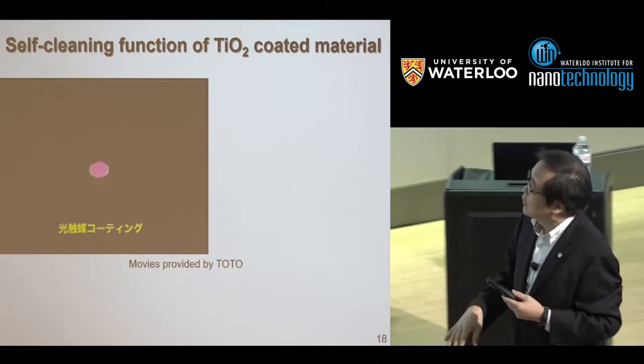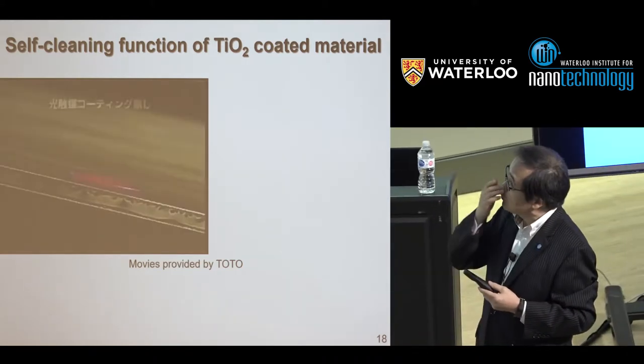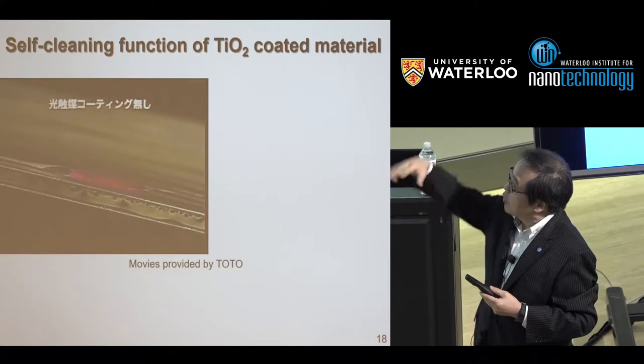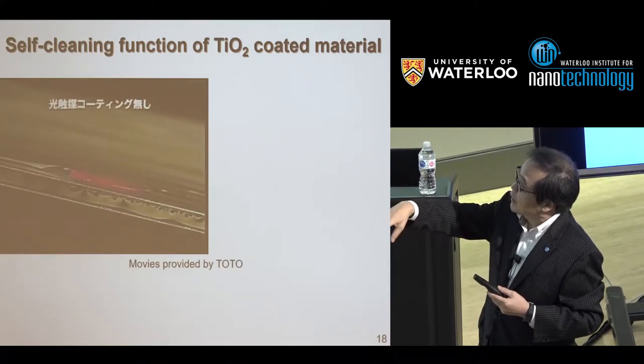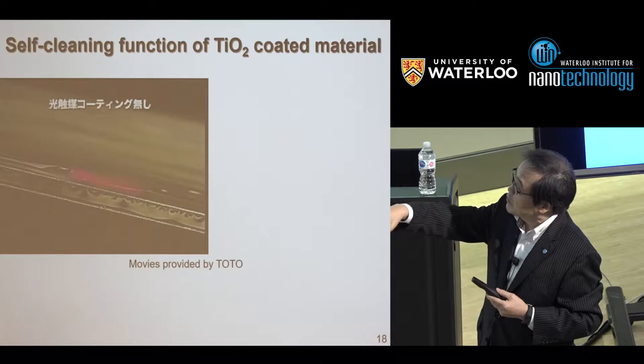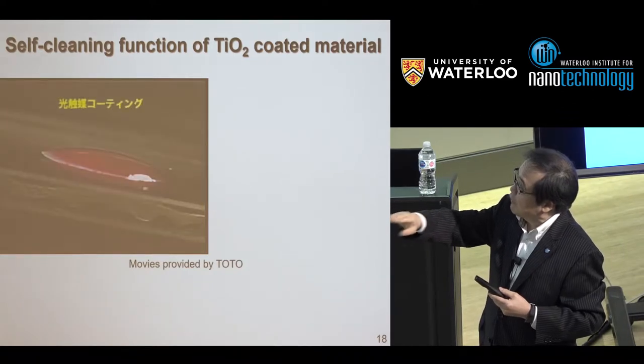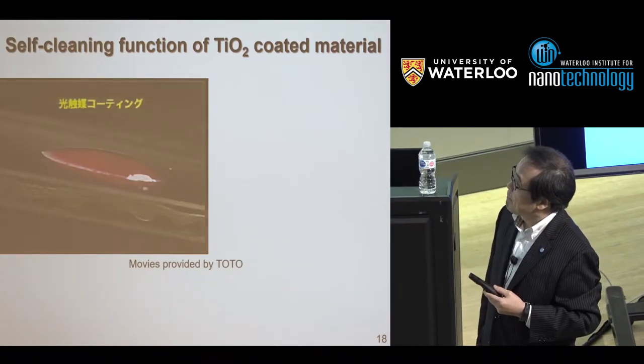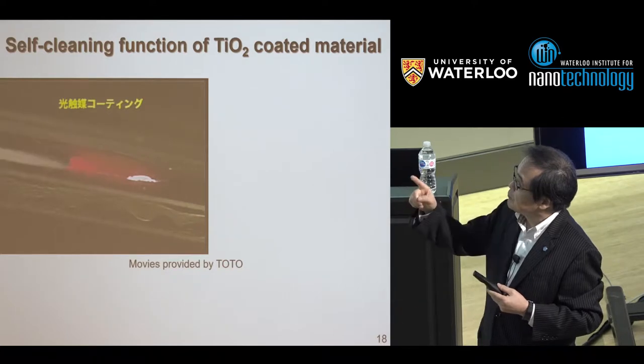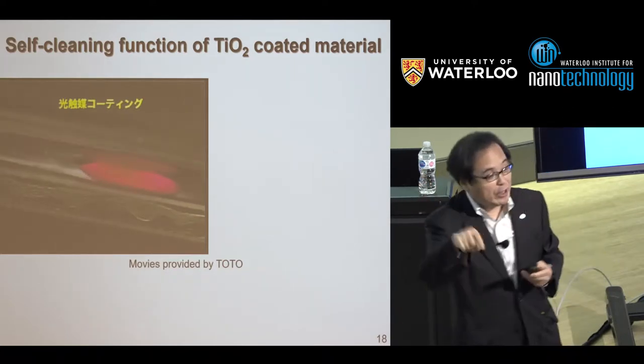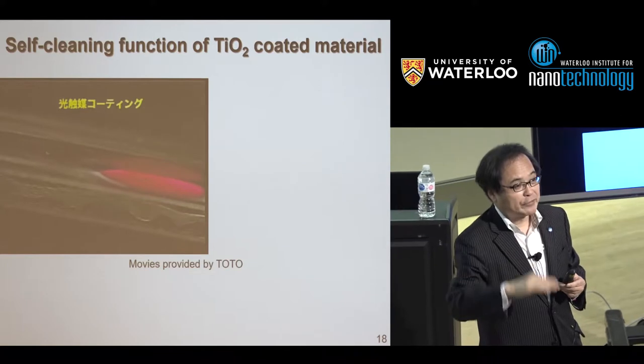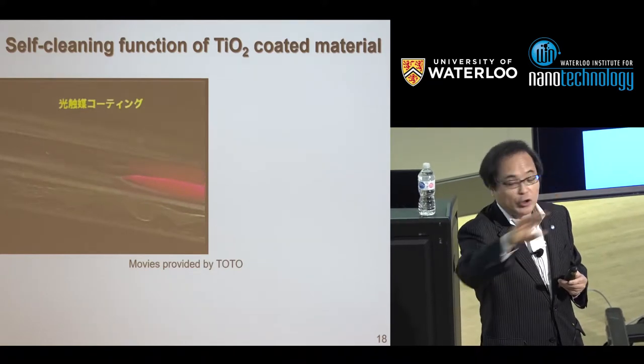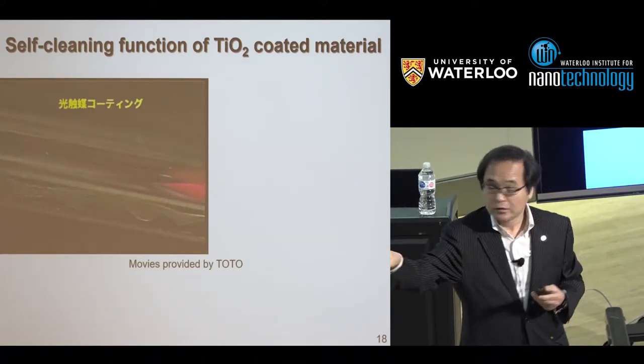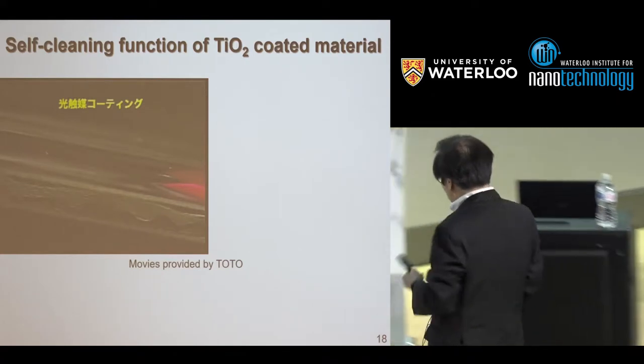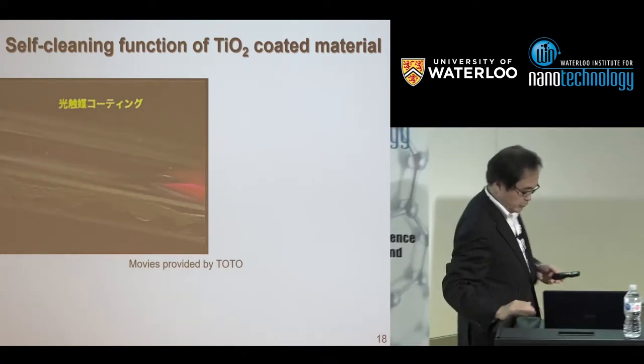What happens? I can show the side view from now on. This is a conventional one. Oil sticks on the surface. But in the case of titanium dioxide, after illumination, the surface becomes so hydrophilic that water comes in between oil and substrate. That's why oil is washed out. So then it gives us a new application.